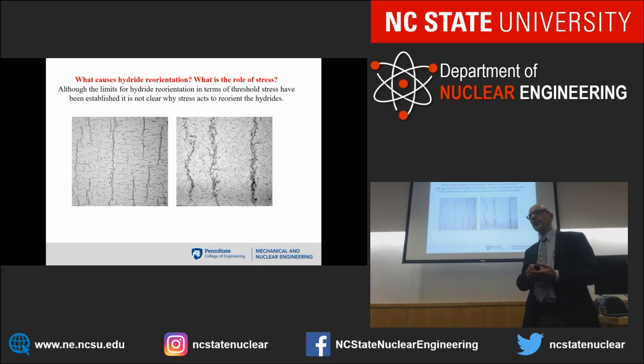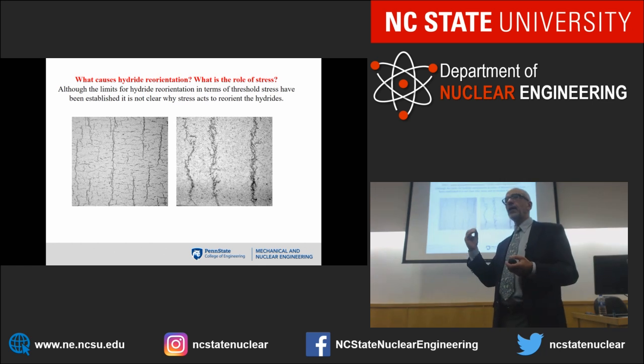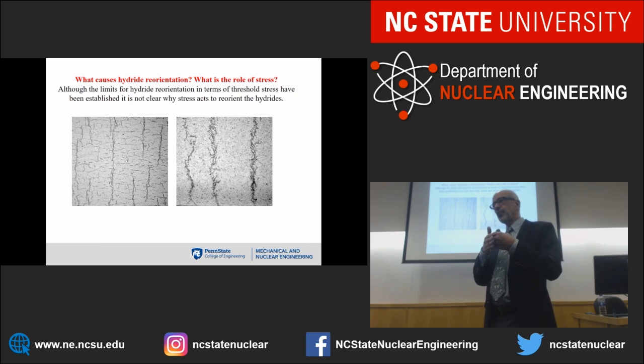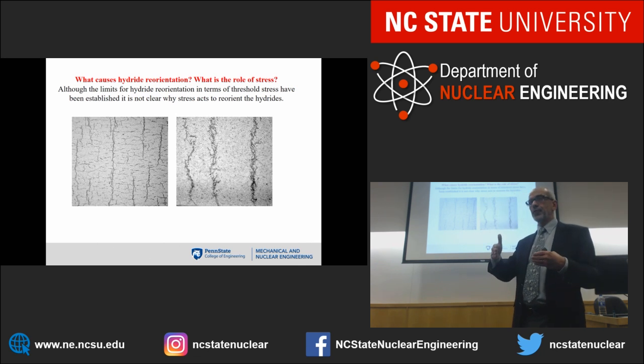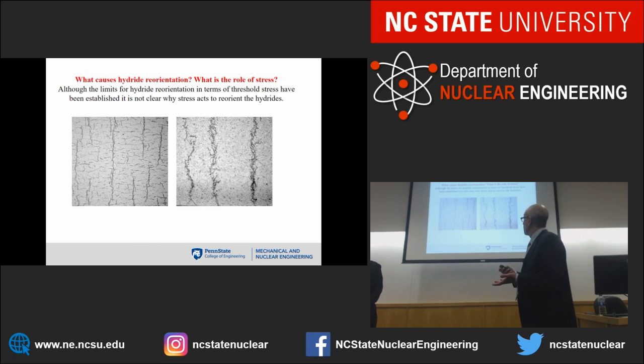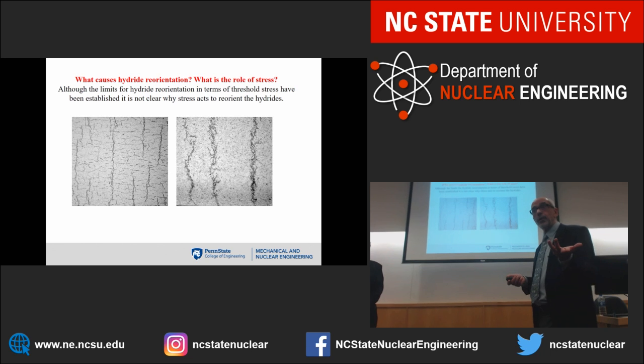The one thing I didn't mention is that the hydrides have a higher specific molar volume than the matrix. So they want to occupy a bigger volume. So they tend to deform the matrix and form dislocations during precipitation. The point defects that you're talking about, you mean for under radiation, right? So they might come and relax some of these.